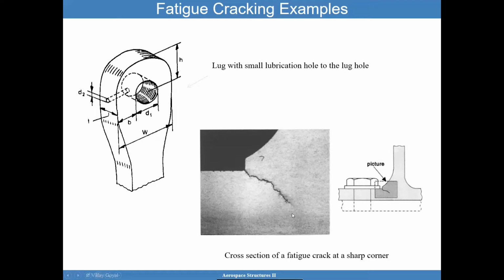What is a lesson learned here is that while you may implement some fillet radii in your application to reduce the potential for fatigue crack initiation or growth, it's important to understand that you may intend something for the drawing, but manufacturing is something else. And so it's important to really inspect and ensure that your part, which may be fatigue critical, is compared against the drawing and that you haven't violated any of the drawing requirements. Otherwise, you may have unintended consequences, and you may have thought that your design was adequate, but it was not.